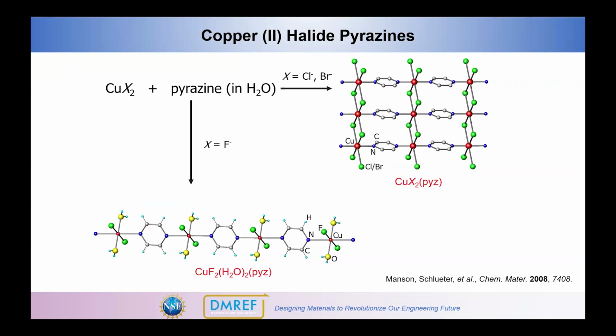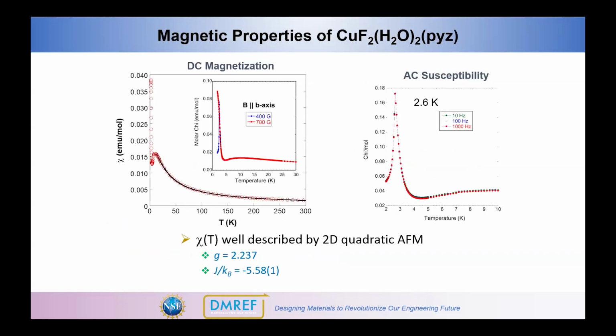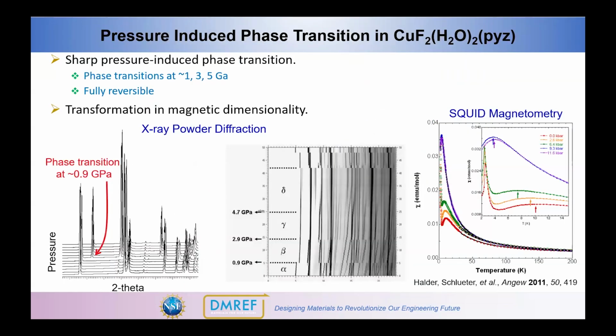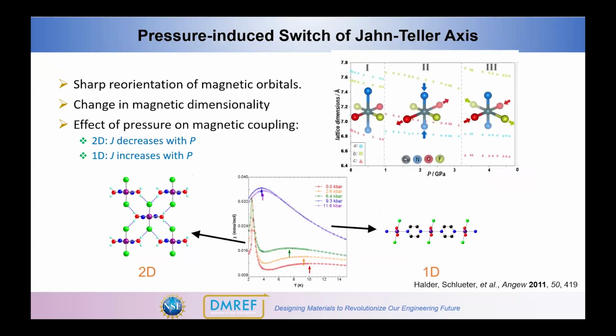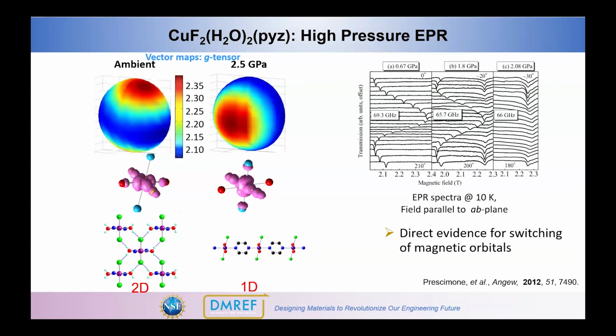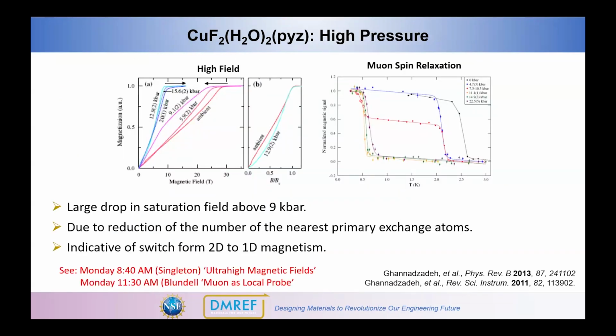And to just quickly explain what happened, we made this copper fluoride hydrate pyrazine coordination polymer, and we noticed that there's a series of pressure-induced phase transitions. And what happens is that as you pressurize the material, you switch the direction of the Jahn-Teller axis, and this can transform a two-dimensional magnetic material into a one-dimensional chain. And so we can control the orbital order and magnetic properties if we can control the orbital orientation of the Jahn-Teller axis.